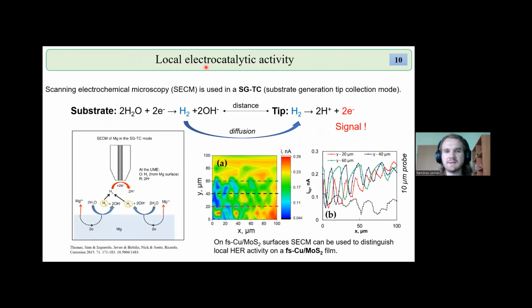We also measured local electrochemical activity, which was done by scanning electrochemical microscopy. Very briefly, it is a method in which a probe of a very small diameter, in this case 10 micrometers, is lowered toward the surface of a sample, which in our case was the molybdenum sulfide film on a femtosecond laser ablated copper surface. A substrate generation tip collection mode is used, which means that on the substrate, hydrogen evolution occurs and hydrogen gas evolves, but preferably not in bubbles, but in a small enough amount to dissolve in the solution. And the tip is polarized to oxidize this gas to obtain electrons. And these electrons are the signal that the potentiostat obtains.